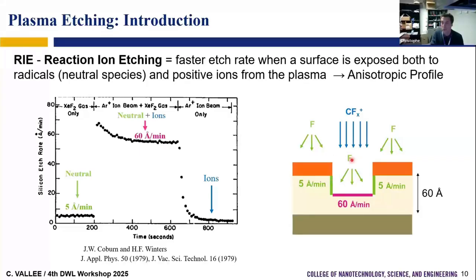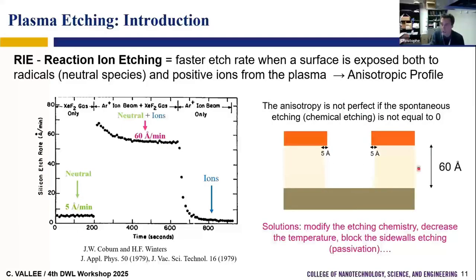While at the edge, you don't have ions, you have only the radical species. So you etch at 5 angstrom. So at the end of your process, when you have removed 60 angstrom, you will only remove, for example, 5 angstrom at the top. So you have not a perfect, but a nearly perfect anisotropic profile.